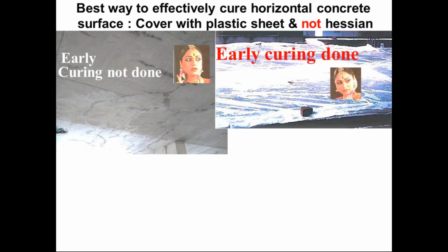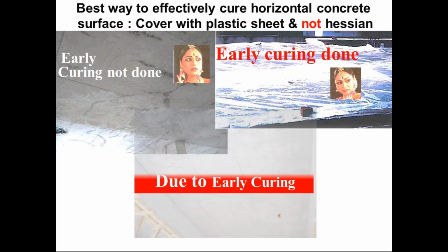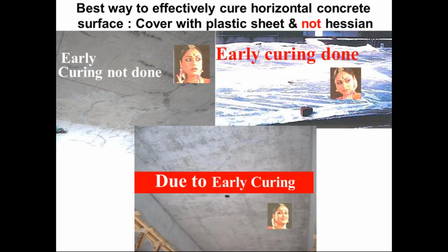The best way to effectively cure horizontal concrete surface is the plastic sheet, as I said earlier. Now, on one of the sites where we had supplied cement, there were excessive cracks. Now, remember, shrinkage cracks can come right through, because concrete is very fresh at that time. And definitely, it will give problems of leakage and seepage. So they have to be avoided at all cost.